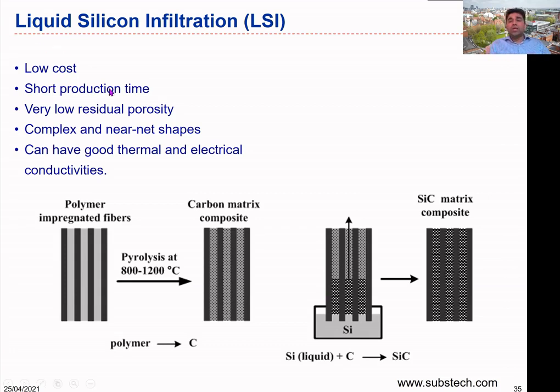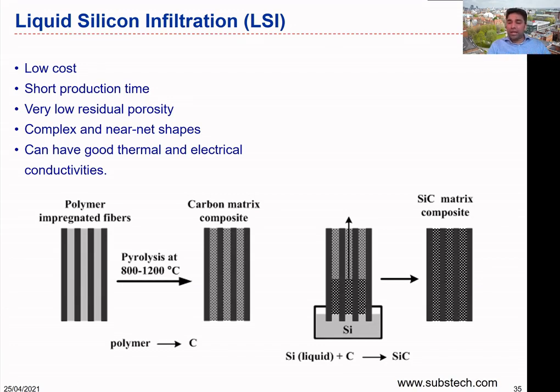Another advantage is very low residual porosity. If you match the conditions properly, we can have a low level of porosity. It is really important to control conditions such as viscosity — that means temperature — and the fiber-to-resin contact angle. If those are controlled properly, we can have porosity at a minimum level. However, there could be some level of porosity if the process is not done well.